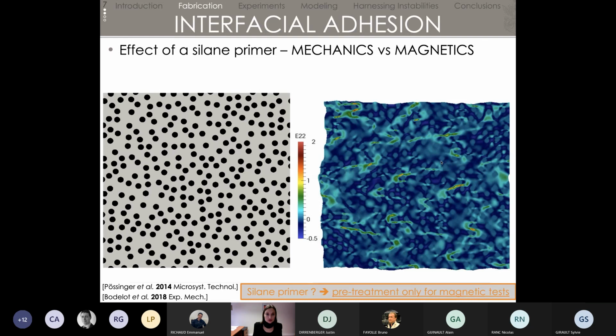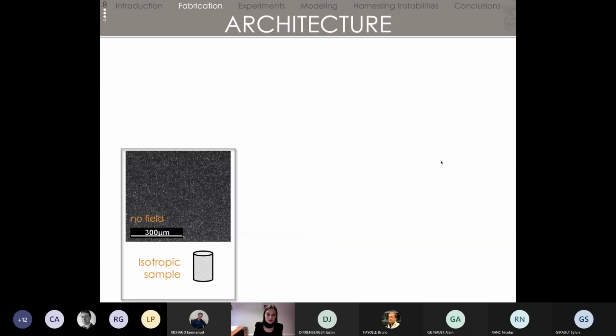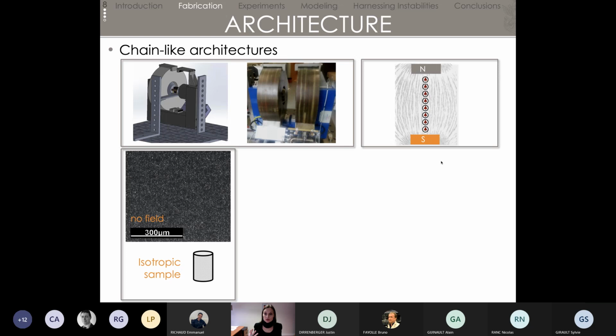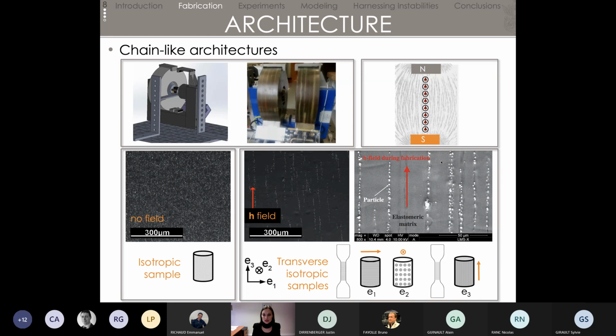Another thing about those samples and materials is the architecture. If we just mix the particles thoroughly and let the mix cure without any magnetic field, we obtain an isotropic sample. Now we can also decide to put the mix as it cures under magnetic field. And since the matrix is still viscous at the beginning, the particles will still have time to align along the lines of the magnetic field.